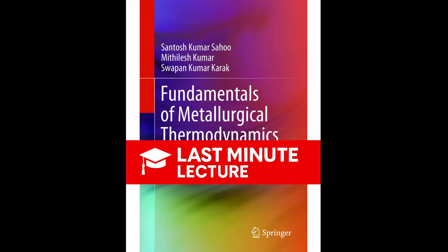So the source material details the complex calculation of the standard free energy change at some temperature T, which we call delta G naught T. This is a multi-step integration process. You start with the known standard enthalpy and entropy at 298 K, and then you integrate to account for the thermal changes. And this whole calculation hinges on Kirchhoff's law, which requires integrating the difference in specific heats between the products and reactants, delta C naught, across the entire temperature range.